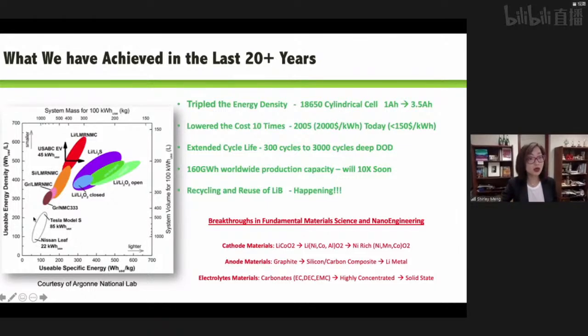So what's being commercialized and what are in the pocket of scientists, because we have demonstrated that the lithium metal paired with the anion redox materials can give you very high volumetric energy density batteries. And if we pair lithium metal with the oxygen or sulfur-based cathode, we can really, really take off in the gravimetric energy density. These kind of batteries are very, very good for flying cars like drones, right? So those roadmaps tell us a very clear message: lithium metal anode must be enabled.